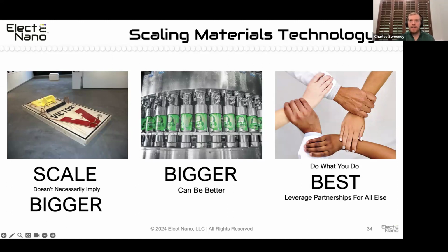It takes the battle hardening of figuring out how to scale a technology, but in the process of doing that, you may see a lot of the gremlins and ghosts in a lab scale process go away, because the process lends itself better to being monitored, controlled, and scaled in a consistent, uniform manner. And so don't get discouraged if you're sonicating a nanocomposite and you get 10 different results 10 different times, even though you did it the same way each time.